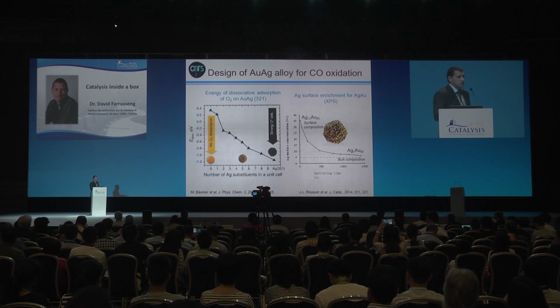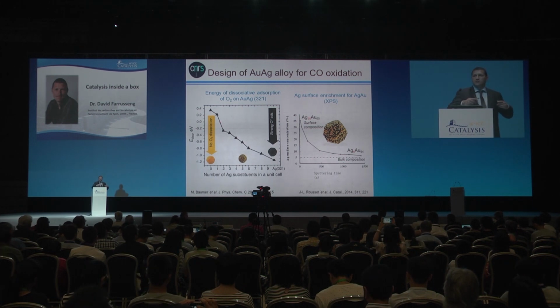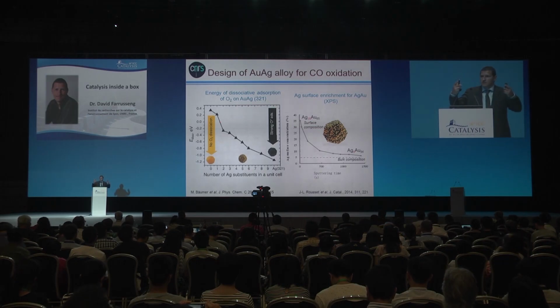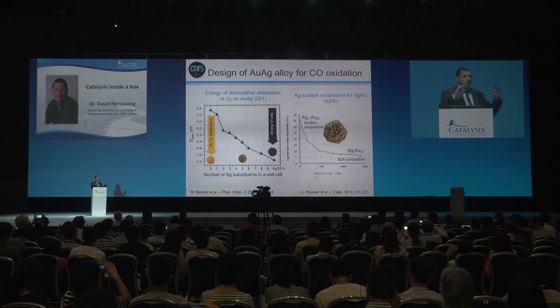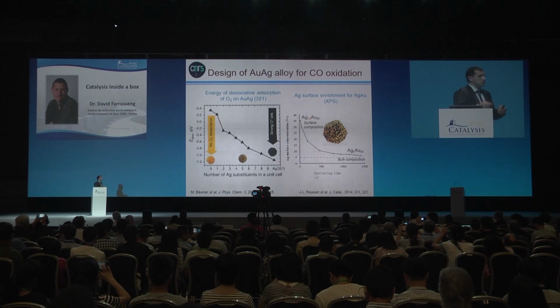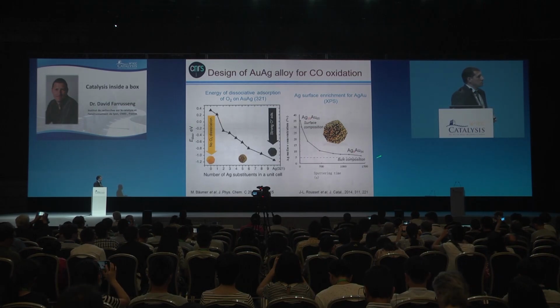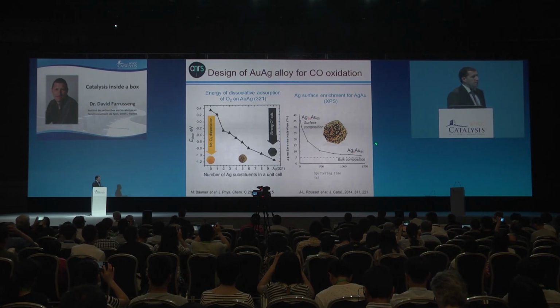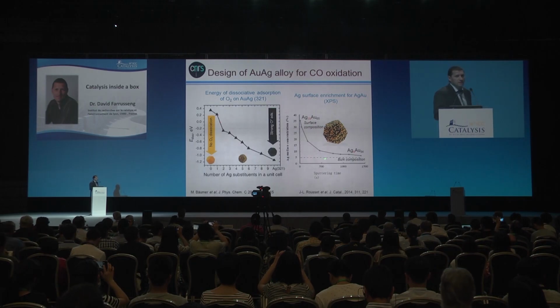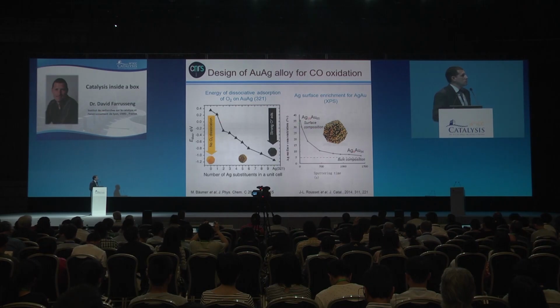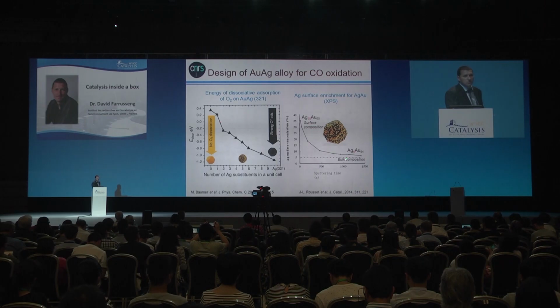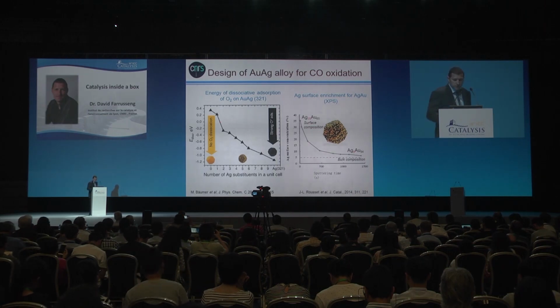Nevertheless, if you start with the 50-50% mixtures, because the silver tends to go to the surface because of its surface tension, the surface will be covered by silver. So the bulk composition has to be very poor in silver, so that then you can reach, for example, a 1-to-2 ratio between silver and gold. So these are the compositions that we have targeted in order to have these surface compositions.